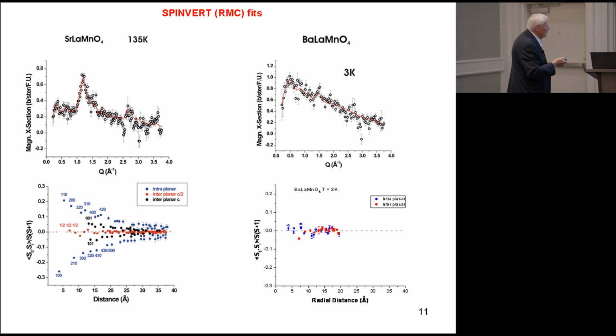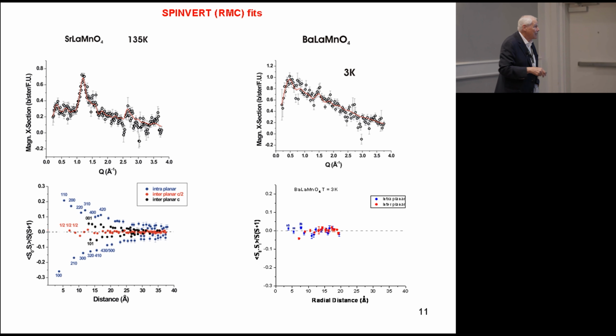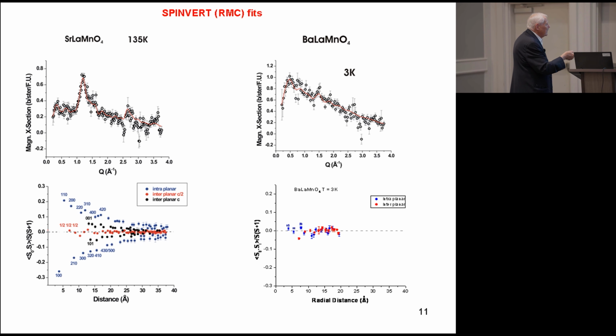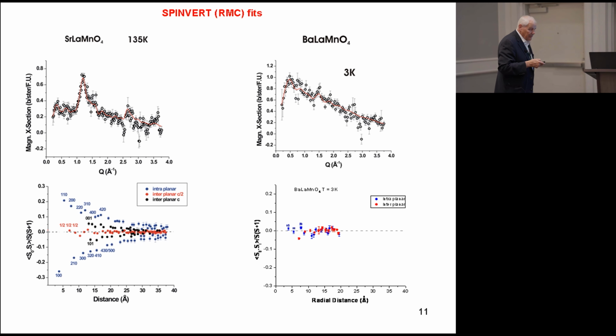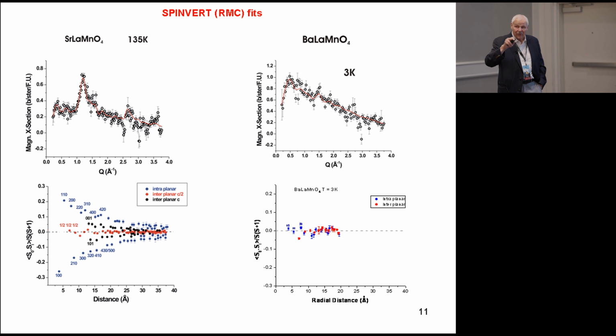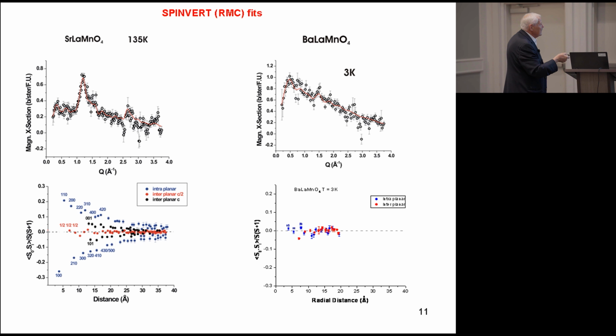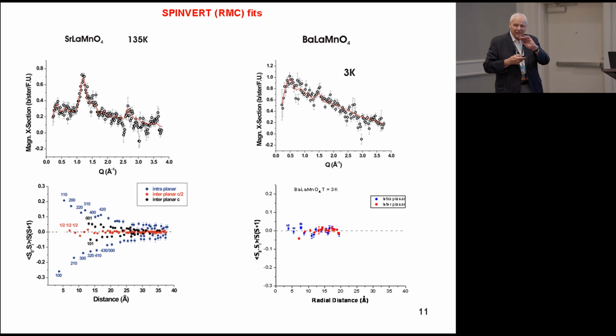And among the ways that you can display the data, here's one. You have the spin correlation function as a function of distance in real space. And these symbols represent real space translation vectors from the origin to the spin. And you can see the intraplanar ones have a strong correlation. And the spins at exactly the 1/2, 1/2, 1/2 layer have no spin correlation. This is a perfect realization of the two-dimensional frustration.